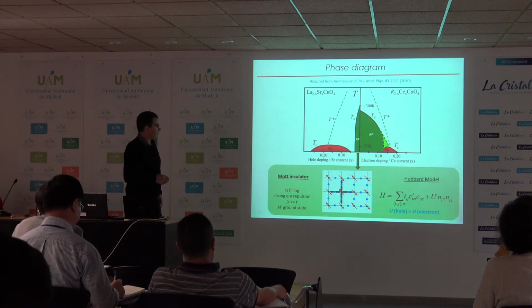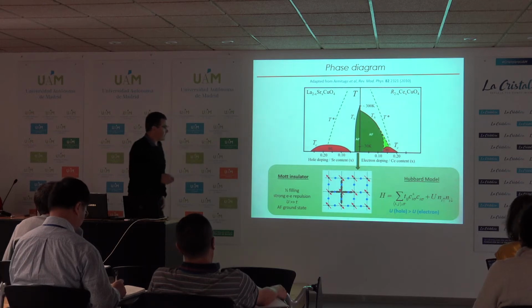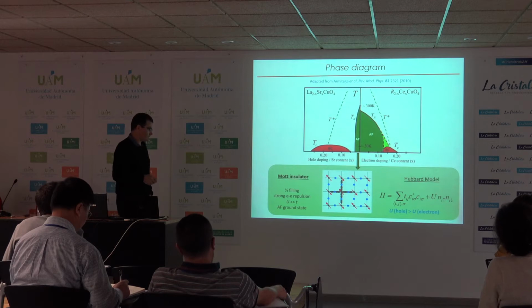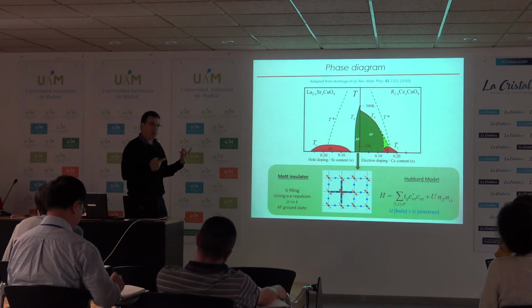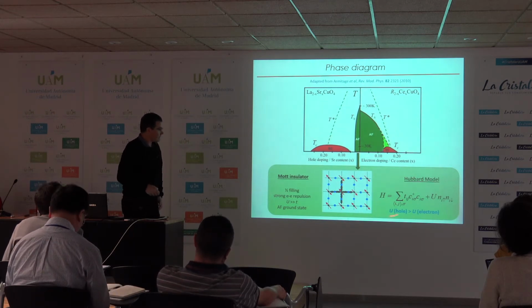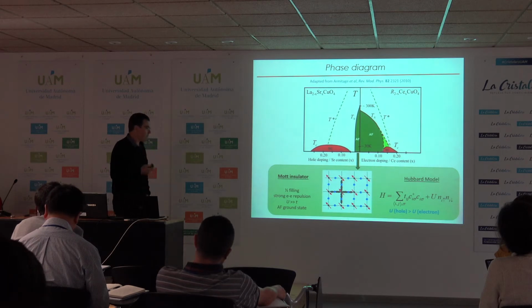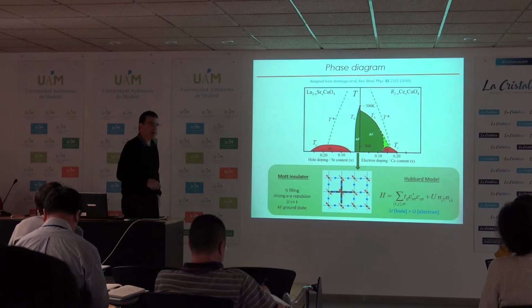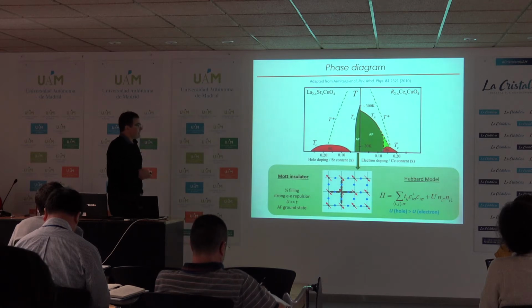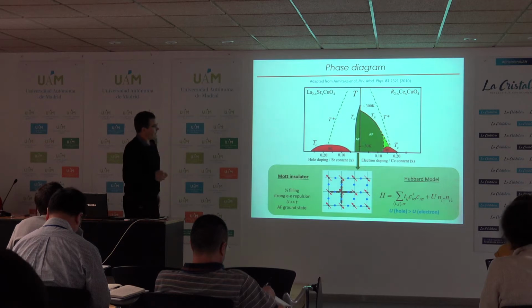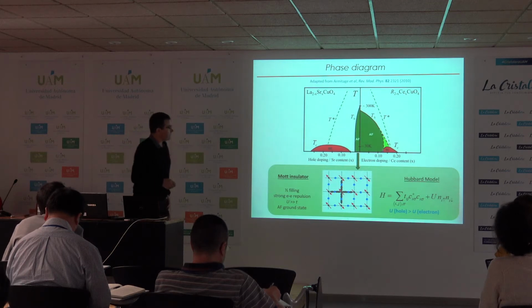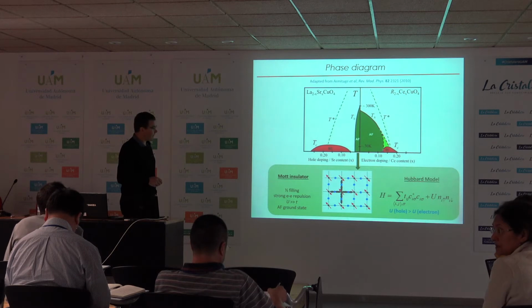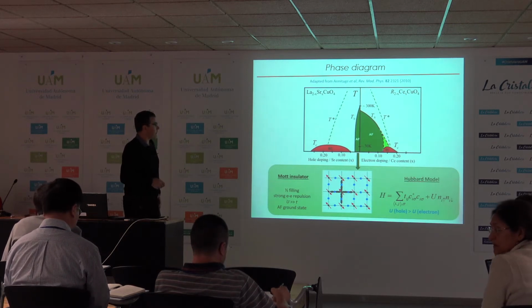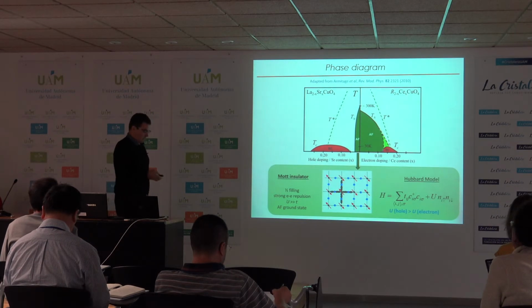This Mott insulator, or the physics of cuprate, is believed to be well described by this Hubbard model, where you have a kinetic energy term and an on-site repulsion term, which is believed to be more important on the hole doped side than on the electron doped side. As you can see, there are a few differences between these two phase diagrams. First, you can see that the antiferromagnetic state extends to much higher doping for the electron compound than for the hole doped compound.